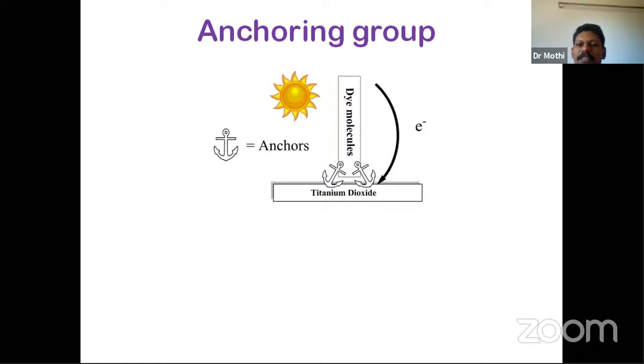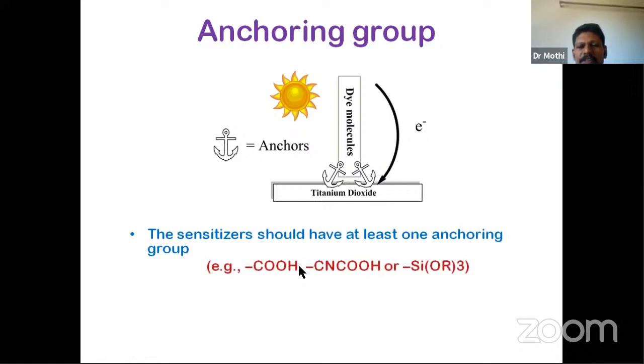So how can we establish this physical contact? We can use some specific organic groups called anchoring groups, rightly said, because they anchor the dye molecule onto the titanium dioxide. Only then can the electron transfer happen. For example, the most commonly used anchoring groups are carboxylic acid groups, COOH, then cyanoacrylic acid, a group containing a cyano group and a carboxylic group, and then silyl groups. These are all very commonly used groups which bind very strongly to titanium dioxide.